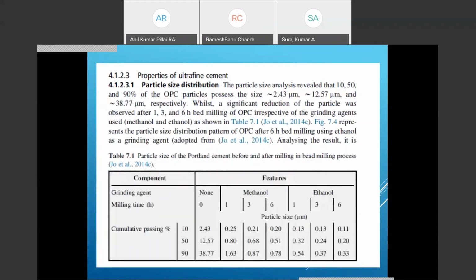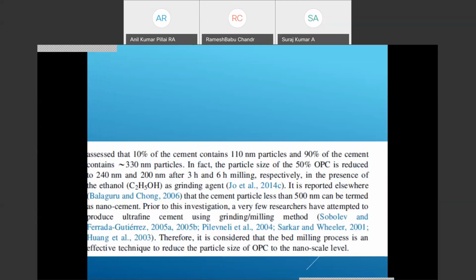It has been observed that the following is the particle size of Portland cement before and after the bead milling process. The particle size distribution of OPC possesses 2.43 micrometer, 12.57 micrometer, and 38.77 micrometer respectively for 10, 50, and 90% of OPC particles. While significant reduction of the particle size was observed after 1, 3, and 6 hour bead milling of OPC, irrespective of the grinding agents used, methanol and ethanol.